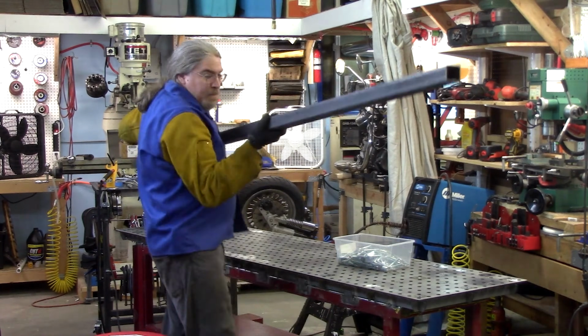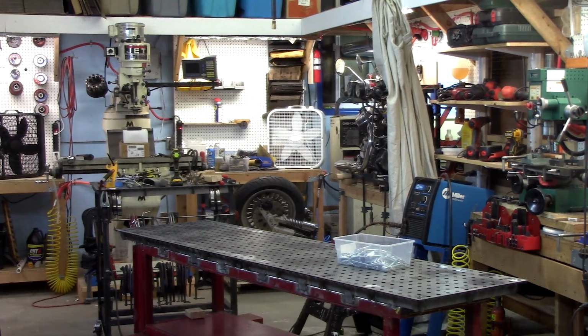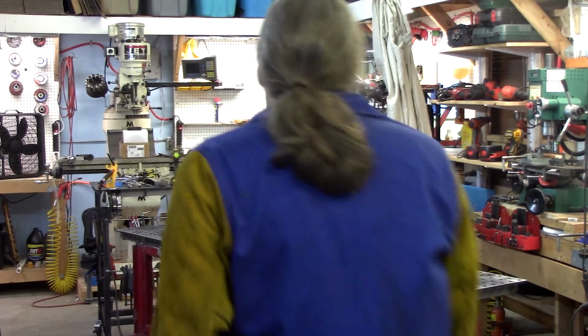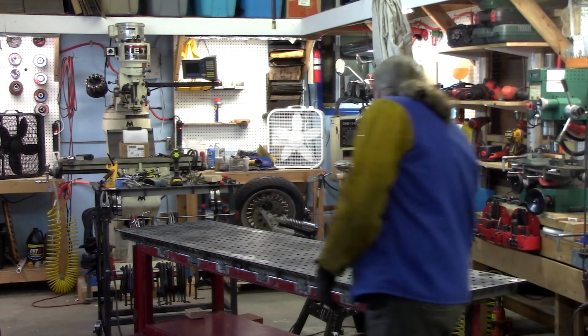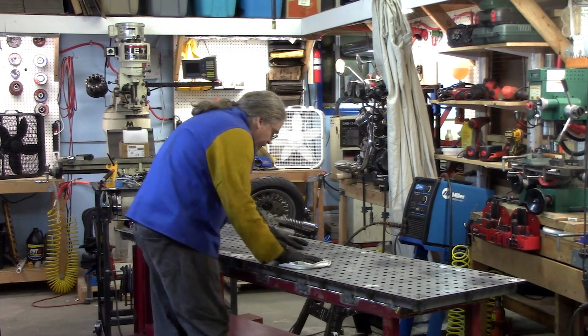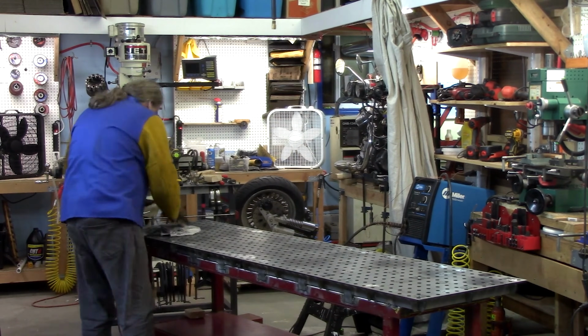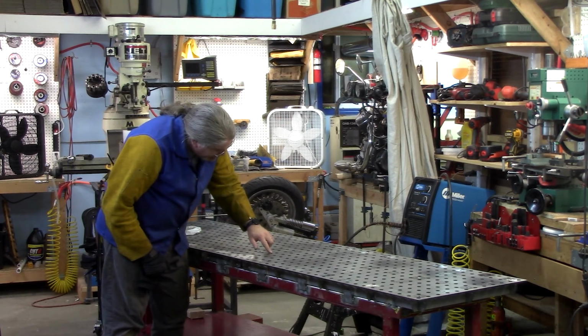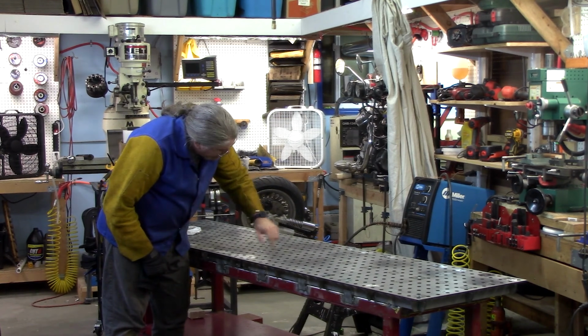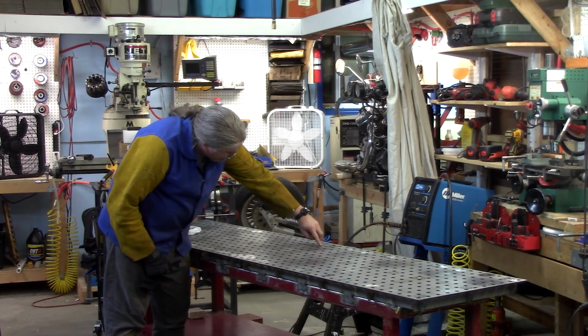With that, the tabletop fabrication surface was pretty much done. I removed the clamps and beams, and wiped the table down. A fingernail test where the tables met was pretty good. It was perfectly smooth across about 80% of the width, with one spot about 2 or 3 thousandths off that I hit with the flapper disc.